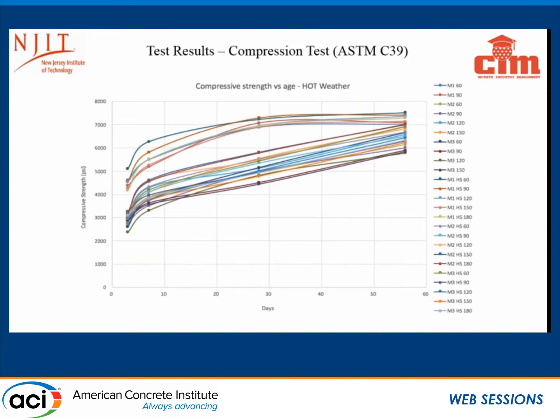This graph has a little bit too much information, but in a nutshell, what comes out of this graph is your strength results, which is the main concern of most individuals where the 90-minute rule is concerned. And it shows here that we pretty much hit the 6,000 PSI target strength regardless, both with and without hydration stabilizers. So doing this research enables us to present actual facts to aid our speaking point that it's quite doable, it's quite achievable.